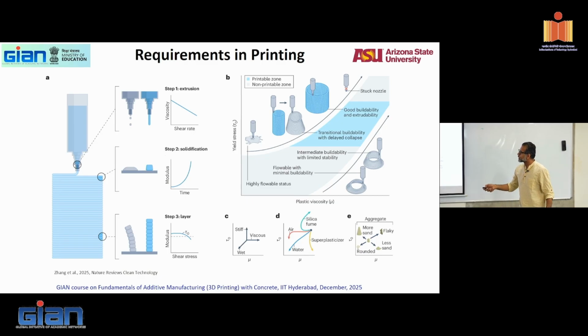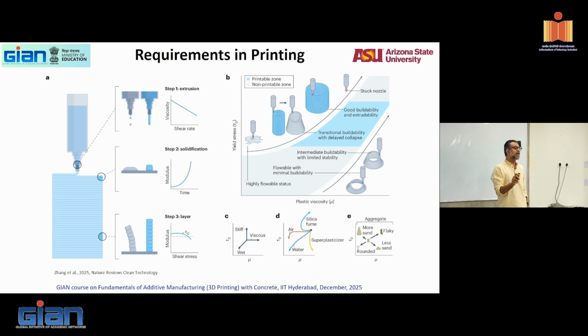And then once you get the modulus, of course, you have shear stresses that are happening. You want it to be built up in a way so that you don't have off-axis stresses building up and causing buckling failures, off-axis failures like that. So that's what you want. Now, if you look at a mix, in this plot this is yield stress, that is plastic viscosity. I'm just using these two parameters because yesterday we learned to measure these two. Stiffness, elastic modulus. The reason I did not say any other modulus is if you're measuring a shear stress, then it becomes shear modulus. If it's shear strain, shear modulus. But if I'm building it up, I'm thinking about axial stresses and axial strains.